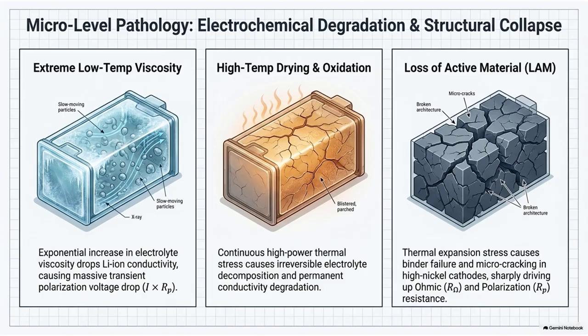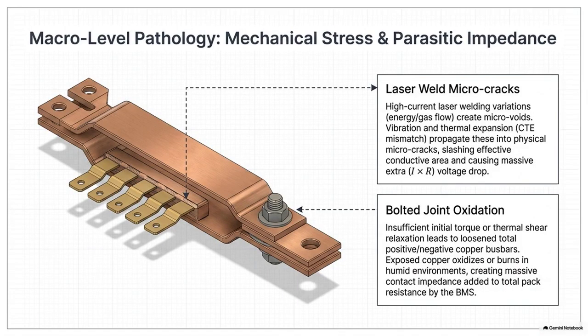Exactly. It is a rapid, cascading failure of the cell's entire internal architecture. The active material is lost, the conductive pathways are severed, and both the ohmic and polarization resistances just spike by orders of magnitude. The battery is effectively dead at that point. Yeah. Okay, so we have the sluggish cold weather electrolyte, the heat-induced drying and parasitic reactions, and the physical micro-cracking of the cathode structure. All three of those manifest mathematically as an intolerable spike in DC internal resistance.